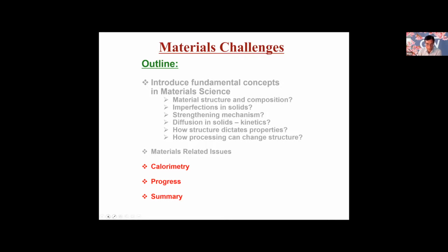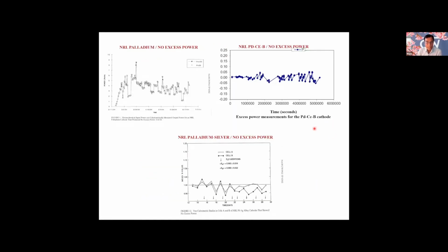So here is the calorimetry work, and you can see here, this is the NRL palladium. We didn't get any excess heat. This is the palladium cerium boron alloys, which we prepared. And also we didn't get any, and again, this is time here, and this is excess heat here. This one here is a palladium silver. Again, we didn't get excess heat. So for all these materials, we tried to find out through calorimetry whether excess heat comes or not. But we didn't find any in any of these alloys or palladium.